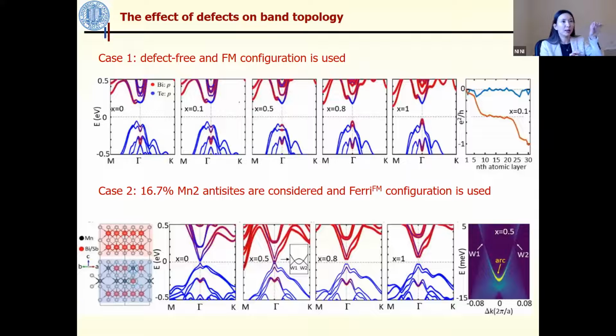So you choose one manganese atom, put it in bismuth, and you choose one specific bismuth site, and you put it in manganese. So I would say this is definitely a limitation, but from the DFT point of view, there is really no better way forward. Okay, thank you.